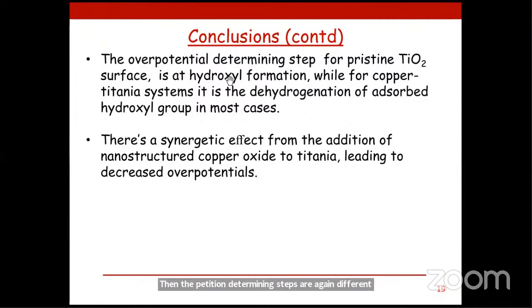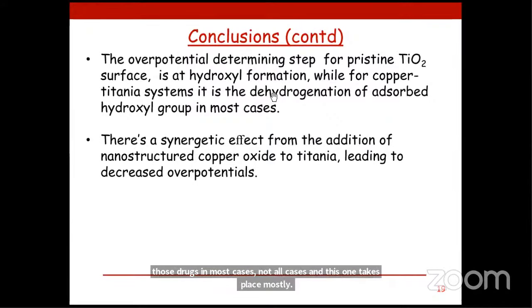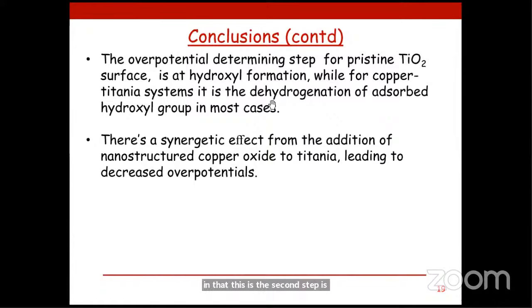Then the potential determining steps are again different. For the pristine TiO2, it's at hydroxyl formation, while for the copper titanium system, it's mostly at the dehydrogenation of the absorbed hydroxyl in most cases. That's not in all cases, and this one takes place mostly in the second step. This is step B in the water oxidation reaction, while the hydroxyl formation is actually in the first step.